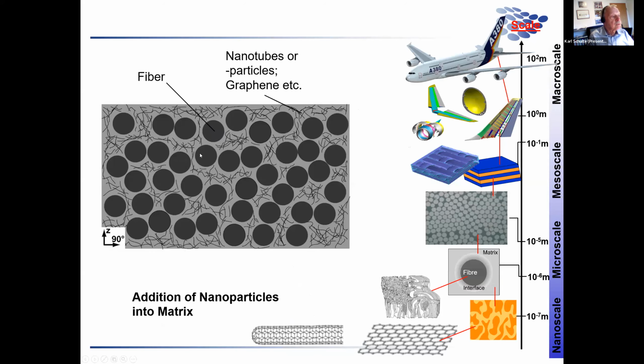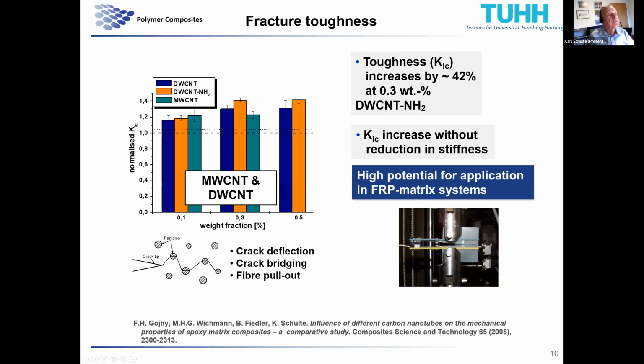Going back to carbon material, first I'll talk about just the matrix filled with carbon nanotubes or graphene oxide. An important point is the damage behavior in a composite material. Fiber reinforced composites, if overloaded, might lead to matrix failure - meaning a crack in the matrix, probably a crack between fibers. If we use carbon nanotubes as a filler in the matrix, as shown in this case...